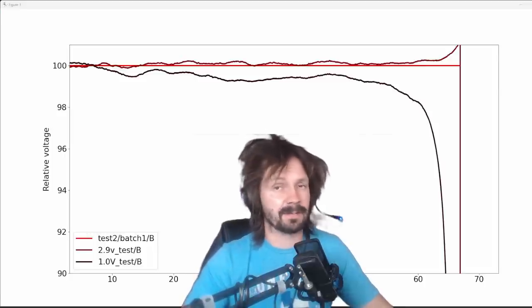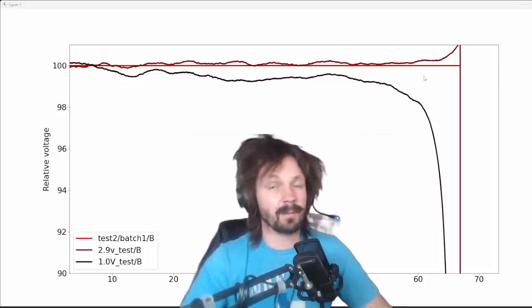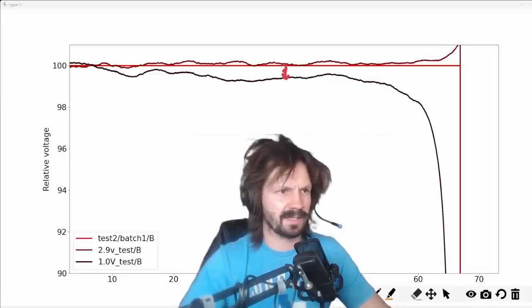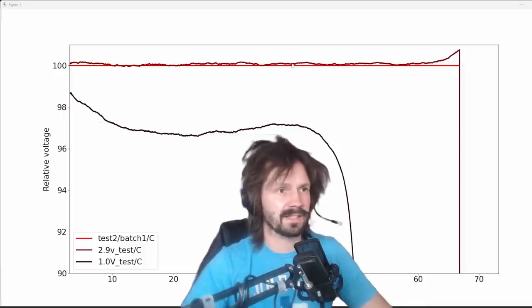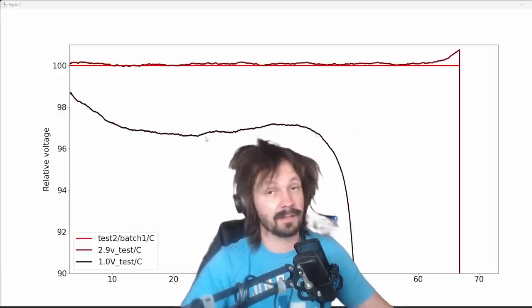MCK V2 battery: second run is pretty much identical to the first run, even somehow a little bit better. But the moment you discharge it to 2.9 volts per cell, the next run will be noticeably slower — less than 1% difference here, but you lose 3 seconds. Now, DOCOM 533 battery — this is a lot. First and second run are pretty much identical, but after you discharge to 2.9 volts per cell, it drops about 3%. So don't do that.